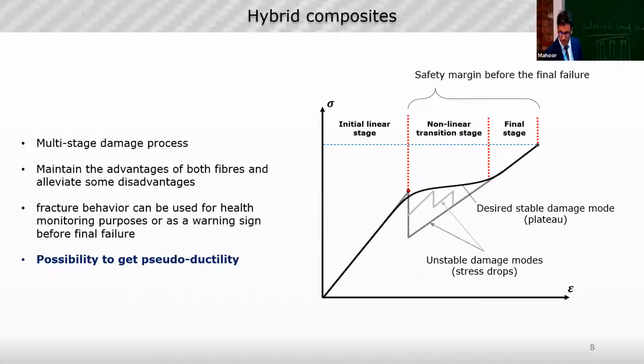As I said, we are interested in creating this multi-stage. First of all, this is necessary to see that we overcome this linear stage, this initial stage. We are in this stage that could show us different scenarios, it could be unstable or stable. This highly depends on how hybrid composites are designed. And with this stage, we are able to see that some damage is occurring inside the composite, before approaching the so-called final stage, which is where the composite, after some extra interval of strain, is going to fail.